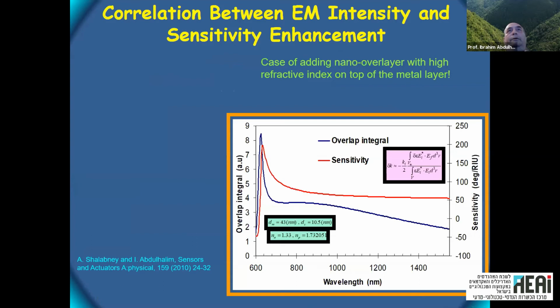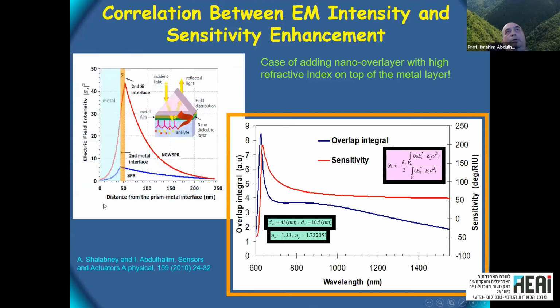So we investigated this a little, and you can see here a quite nice correlation between the overlap integral, that's the blue curve, and the sensitivity of a sensor, the spectral sensitivity. Sorry, actually it's the angular one versus wavelength, depending on the wavelength. And we did that for one special case where we have a metal, and on top of it, there is a small layer, like 10 nanometer of silicon, which we found improved the sensitivity, and we wanted to explain it. Actually, that's how we arrived at it.